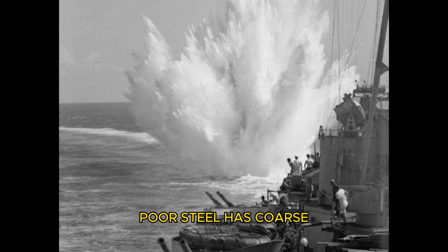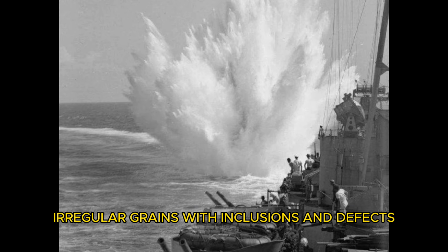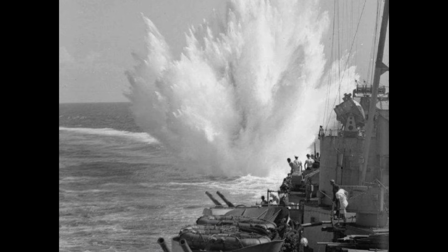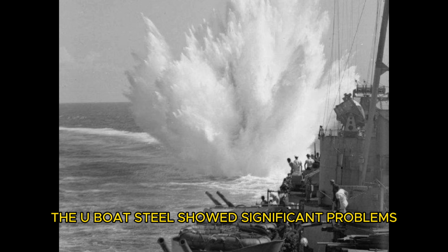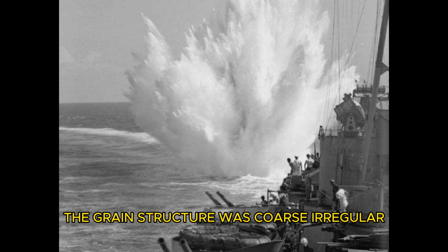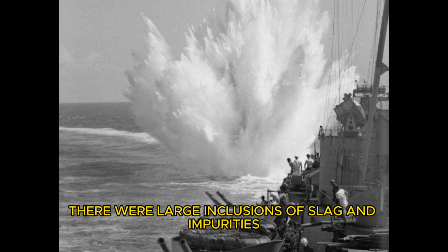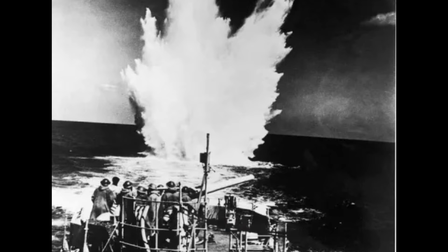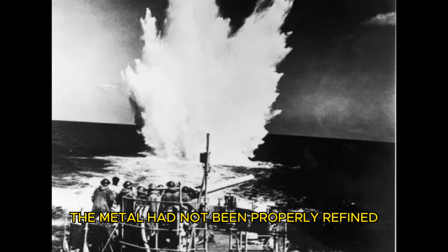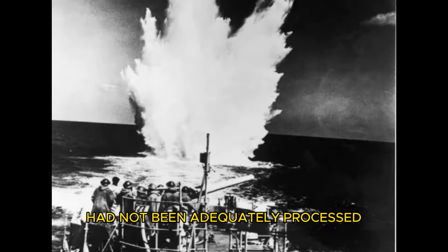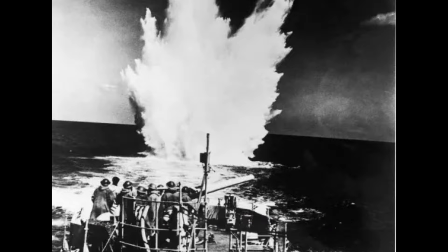Poor steel has coarse, irregular grains with inclusions and defects. The U-boat steel showed significant problems. The grain structure was coarse, irregular. There were large inclusions of slag and impurities. The metal had not been properly refined, had not been adequately processed. It looked like steel made in a hurry with inadequate quality control.